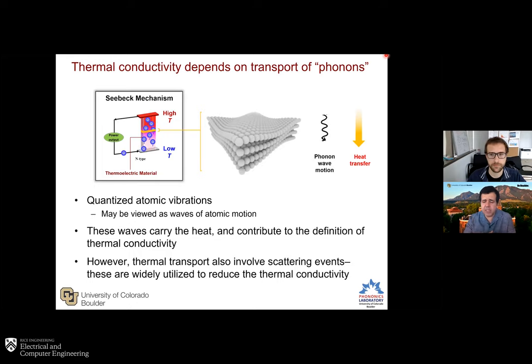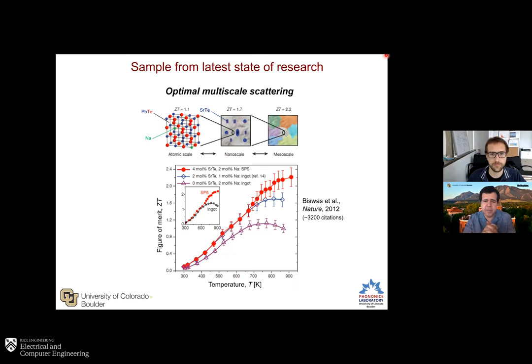So a lot of work has been done over the years, especially the last two decades, with the advent of nanotechnology, to specifically use the notion of scattering very intelligently to reduce the thermal conductivity. And of course, try to do that without affecting the electronic properties. So I'm going to show an example paper here that is very interesting and has been very well received since 2012. This paper targets that strategy whereby you can reduce the thermal conductivity at different scales. At the atomic scale, you can take some crystalline material, lead telluride, for example, and introduce sodium impurities. And in doing so, you effectively scatter some of the phonons at certain length scales.